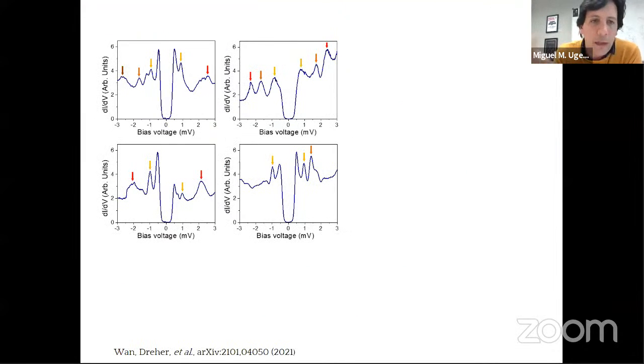Here I show you 4 examples taken with different tips, physical tips, not just tip apex, on different samples on different days. Everything was different, and still we see very often, or almost always, these characteristic peaks. As I said, they are in general quite symmetric with respect to the Fermi level, and there is some sort of symmetry, and they are quite equidistant from each other. It's not always like this.